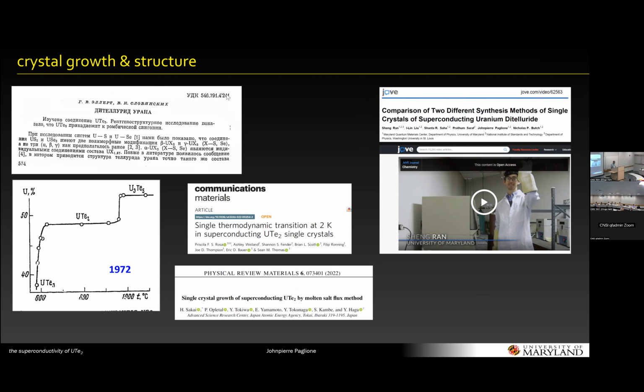And yeah, as I said, there's very old work. I think this is probably one of the first papers, from, I forget the year, but many years ago. Oh, 72, sorry, 1972. And even there, they commented that uranium telluride exists very close to these other phases, other uranium tellurium phases, and that's part of the challenge: when you grow this material, you have to avoid these so-called contaminant phases. And there's a sort of window. So this is a current challenge in the community, to try to understand when you use different temperatures and so on in this growth, and you get slightly different properties, why is that? And it's going to need some more detailed looks at the TEM and things like that.